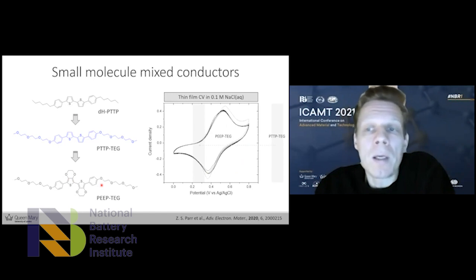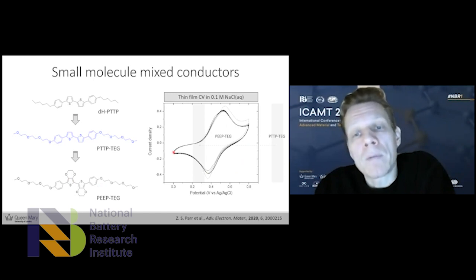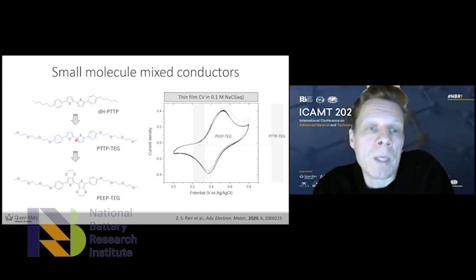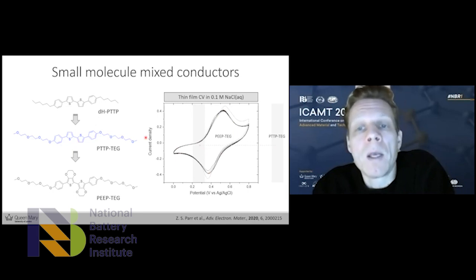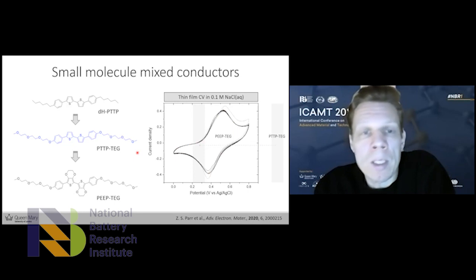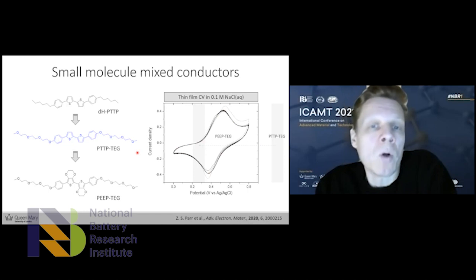get this molecule here, and you can see now the cyclic voltammetry of a thin film in aqueous electrolyte. It switches very nicely. We have a very well-defined oxidation wave, and again, when we come back, we have a very well-defined reduction peak. So it's a very reversible process in the solid state in aqueous electrolyte, and you can see the oxidation potential has decreased quite significantly compared to the thiophene derivative above, which is all good indications of mixed conduction in the solid state and potentially a good OECT material.